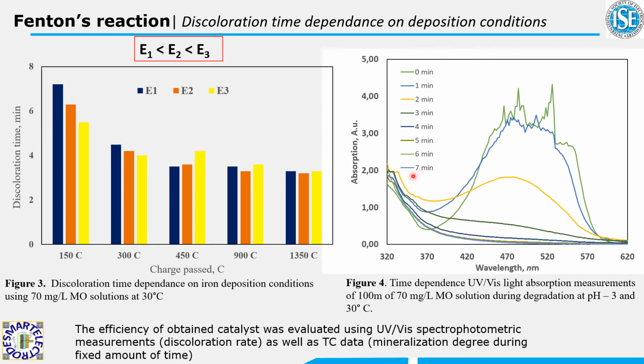The start of the measurement was chosen so that the ending would be as close to the discoloration time as possible. As we can see from the data, with increasing the potential, the discoloration rate increases and the time becomes shorter. This is caused by bumpy deposits obtained using higher potentials. Also, a further increase in the discoloration rate can be achieved by increasing the amount of iron on the foam. At around 450 coulombs, the minimum can be reached and the discoloration time does not change much afterwards. This is the result of enough iron and very fast corrosion of iron on the highly porous copper foam surface.